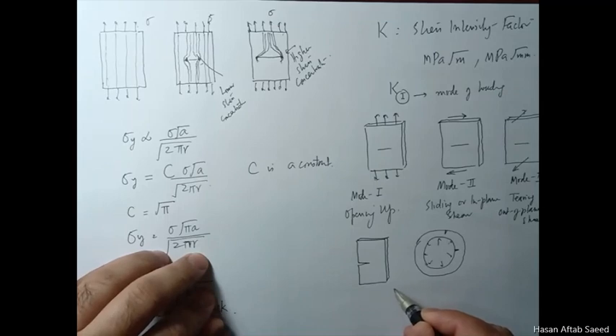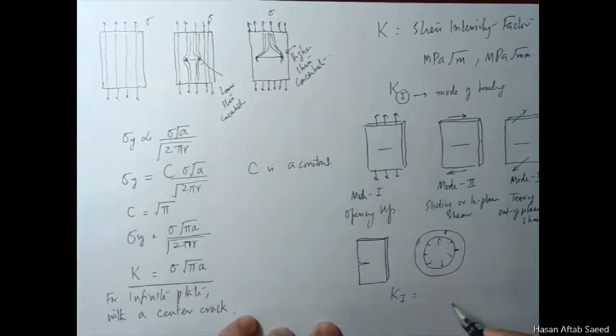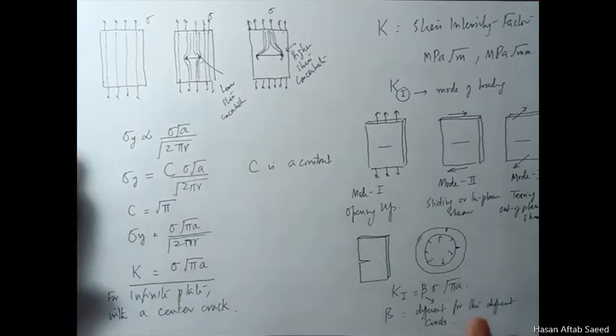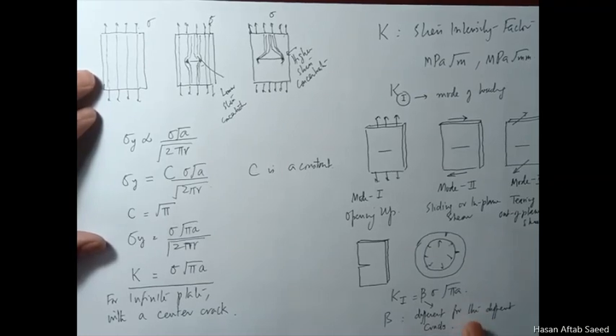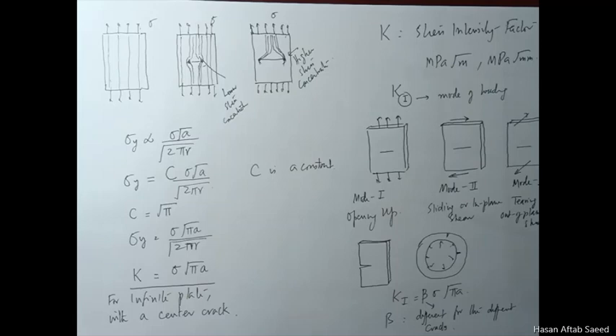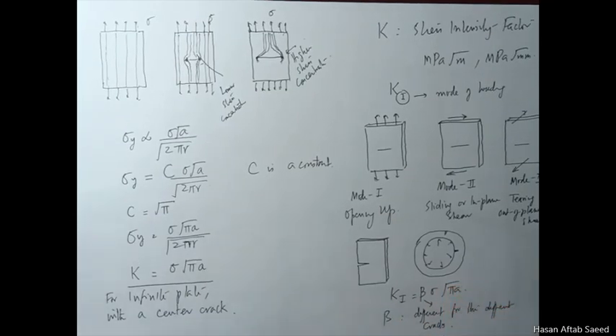What do we do when we encounter these situations? Very simple. This K1 becomes not sigma root pi a, but here there's a constant beta. Now this beta will again be different for the different cracks that you encounter. And where do we get these betas from? We have convenient tables, and in your textbook also we have them. Theory of elasticity deals with them. Finite element analysis can be used, but we won't go on calculating these betas for any situation we encounter. We'll just look up the values from some table.